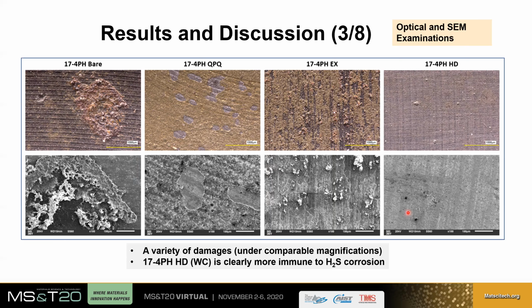This is in stark contrast with, let's say, the 17-4 QPQ. So here we see a very golden coating. We see islands that are different. And when you look in the SEM, essentially what you see is that wherever you have those little islands, actually a piece of the surface treatment is gone. Okay. So we do have some spalling happening here.